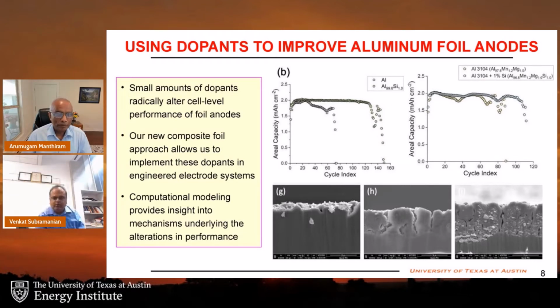One issue is whenever you have a solid metal foil, one will always be worried, how am I going to have lithium diffusion into the material? As you see here with one of these materials, this is the starting point. As you keep on cycling, they create their own pores. So through that, the electrolyte can move through, as well as lithium ions can move through. So that's the beauty with this method of making foil anodes.